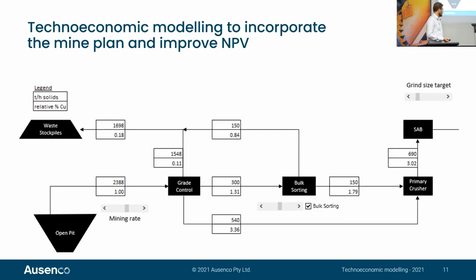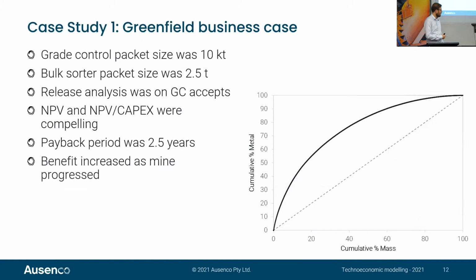So I've got a couple of case studies on this. The first one is a Greenfields business case where it was very high level. We were looking at the grade control packet being about 10 kilotons, but the bulk sorter was able to sort over 2.5 tons. And we were able to look at the release analysis on the grade control accepts. And the NPV and the NPV on CapEx were very compelling. So when we did the economics on that, it was very compelling, and you can see how far that is off the parity line there.